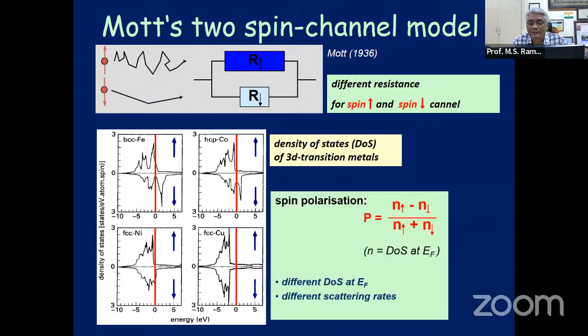In brief terms, one can experimentally realize Mott's 2-spin channel model by creating these multi-layers. I can create one layer that has high resistance, the other layer that has low resistance, and then when you look at the difference, that is delta R, and that delta R is what is required in certain devices, called magnetoresistance devices.